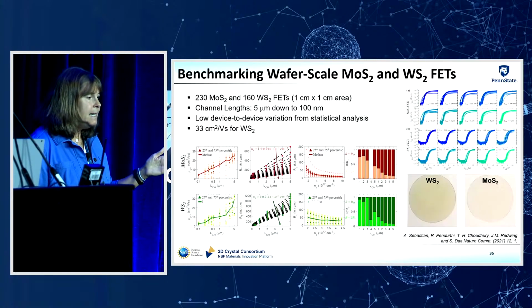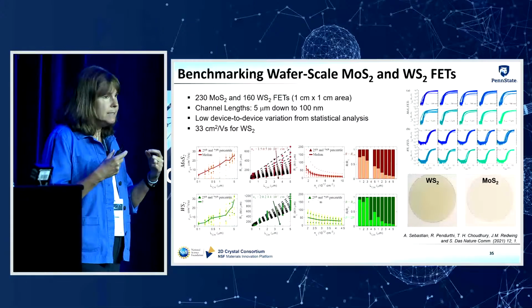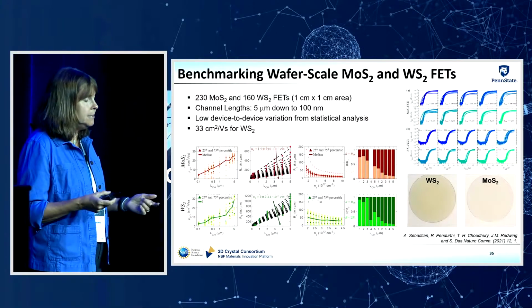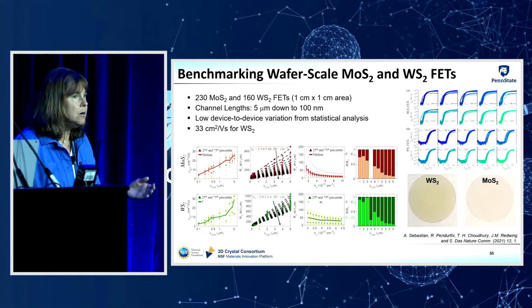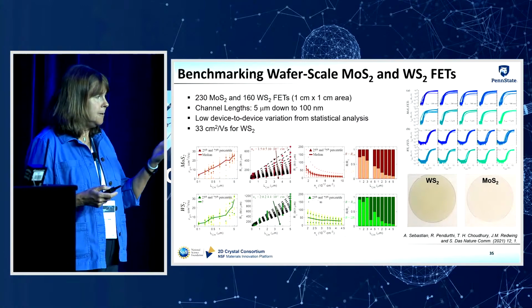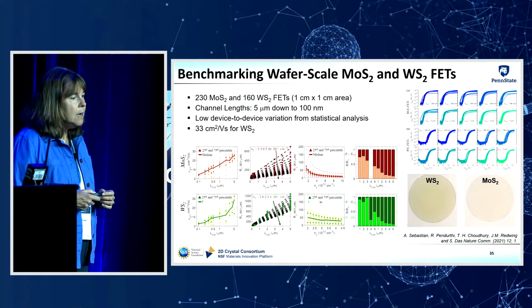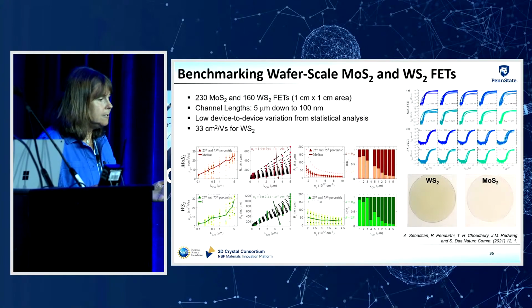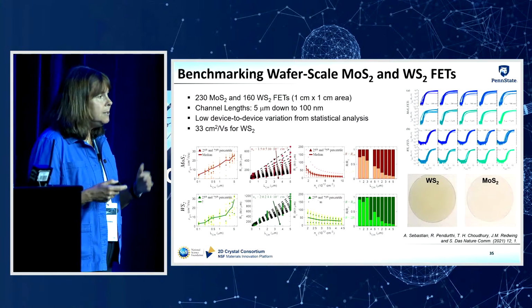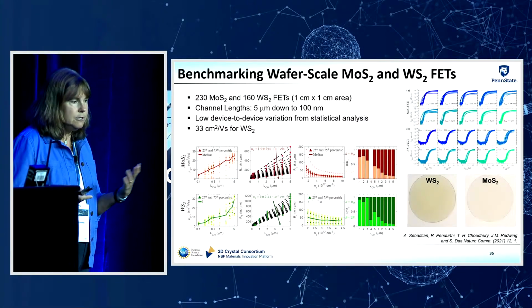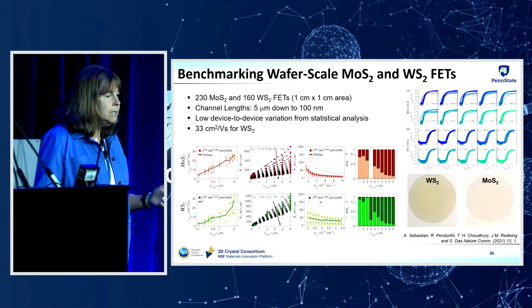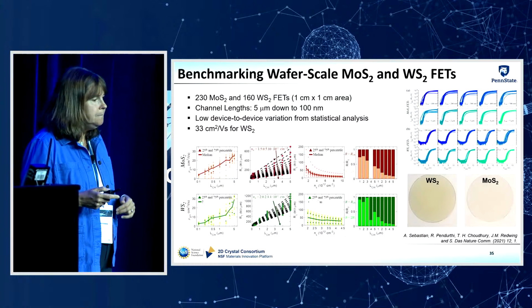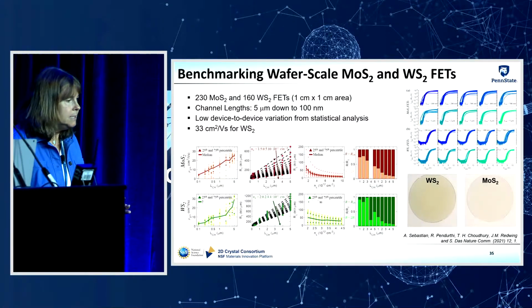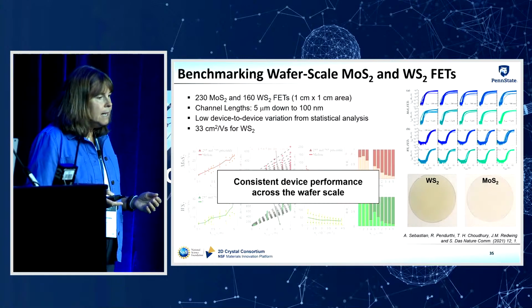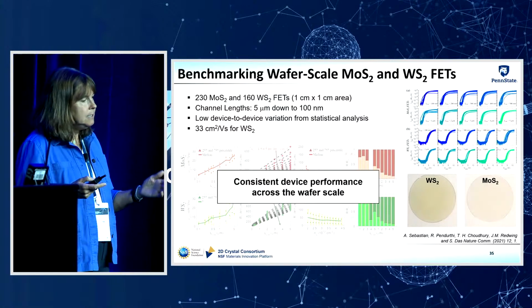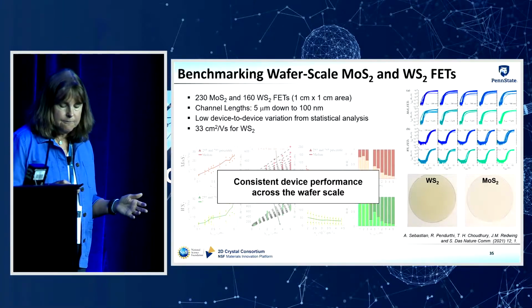So the nice thing about having wafer scale monolayers is now you can start to make a large number of transistor devices and get some statistical data on their performance. So this again is some work from my colleague Saptarshi Das's group, where they fabricated several hundred molybdenum disulfide and tungsten disulfide FETs with channel lengths varying from 5 microns down to about 100 nanometers. They saw very low device-to-device variation. So that enabled them to do some statistical analysis of the device performance. And the upshot here is that they observe very consistent device performance across these wafer scale films.